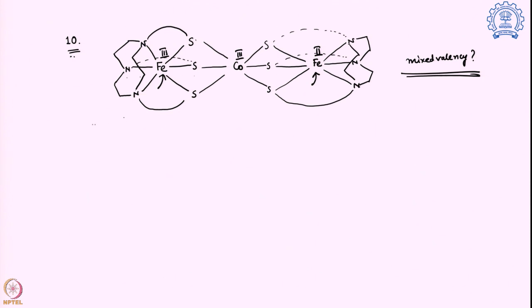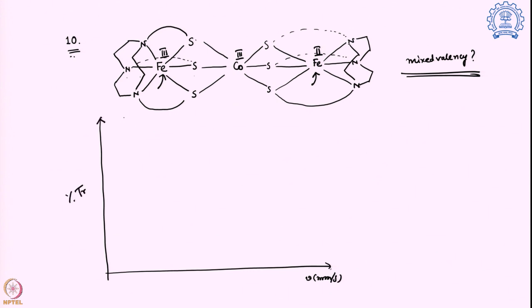So when we first started looking into the Mössbauer spectroscopy, I am drawing the graph. It is the transmittance and it is the velocity, which is coming from how I am moving the Mössbauer source with respect to the sample, with respect to the Doppler effect, that is actually represented over here, which is a representative of the energy scale over here. So when you first do that at higher temperature, by high temperature I mean 353 Kelvin, so it is almost 80 degree centigrade, quite hot. Over there we are seeing only one set of iron centers.